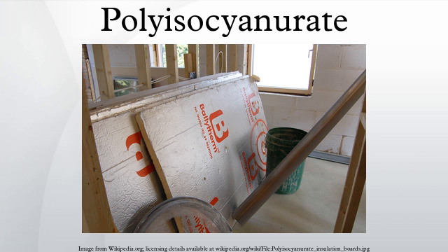PIR typically has an MDI polyol ratio, also called its index, higher than 180. By comparison, PUR indices are normally around 100. As the index increases, material stiffness but also brittleness increase, although the correlation is not linear. Depending on the product application, greater stiffness, chemical and/or thermal stability may be desirable. As such, PIR manufacturers can offer multiple products with identical densities but different indices in an attempt to achieve optimal end-use performance.